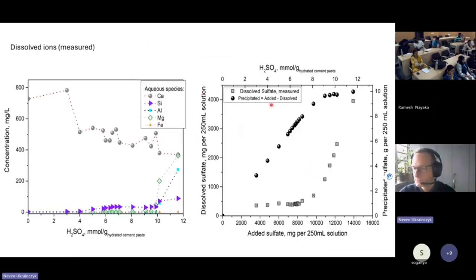Also, the dissolved ion. But for sulfuric acid, actually, there was a very simple correlation with the amount of acid and the dissolved sulfate, and also precipitated sulfate. So the more sulfate you add, the more calcium sulfate you precipitate, and also dissolved. This is the dissolved one, and this is the precipitated one. So here is like a linear correlation, but then later it becomes non-linear.